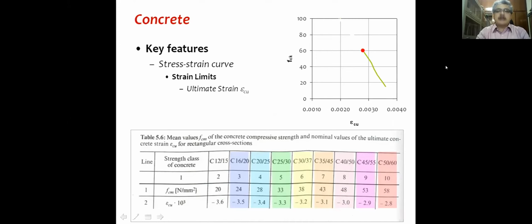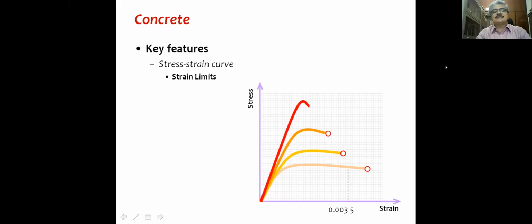Most in the initial days, experimental results were up to about M40 and M60 grade of concrete. Today we have higher experimental results for that, but essentially extrapolating or extending this shows how the ultimate strain reduces. This is essentially the nature of the stress-strain curve of concrete when testing is done. So the ultimate strain reduces with increasing grade of concrete, but interestingly, the strain at which the peak stress is attained increases.